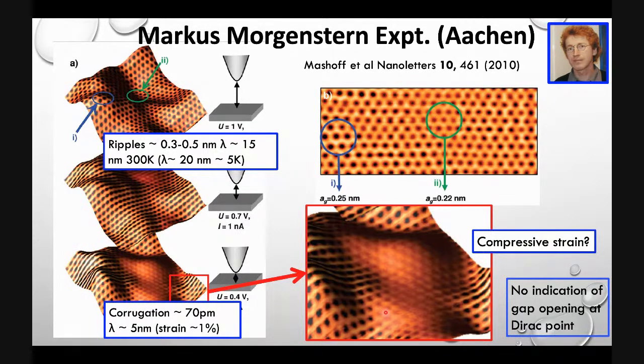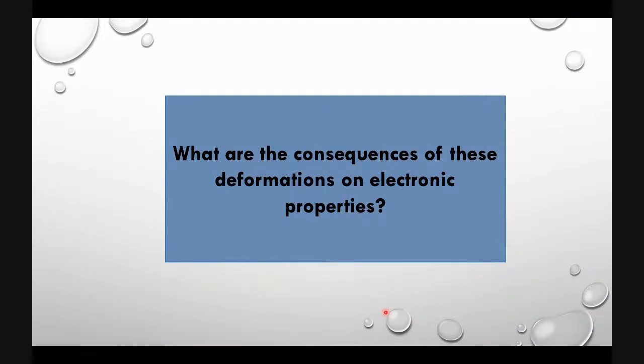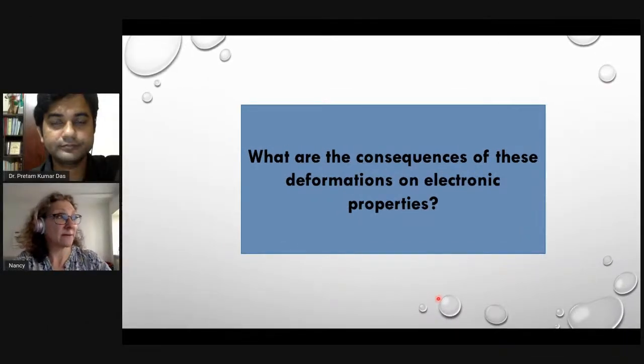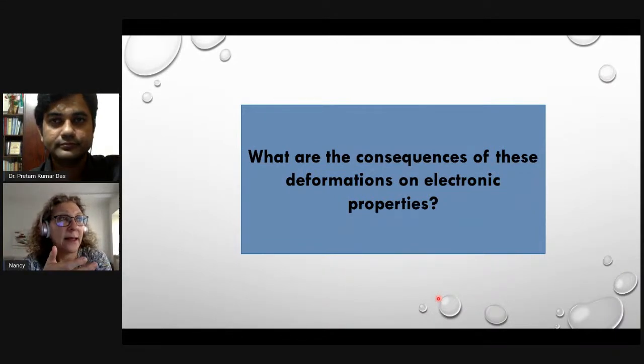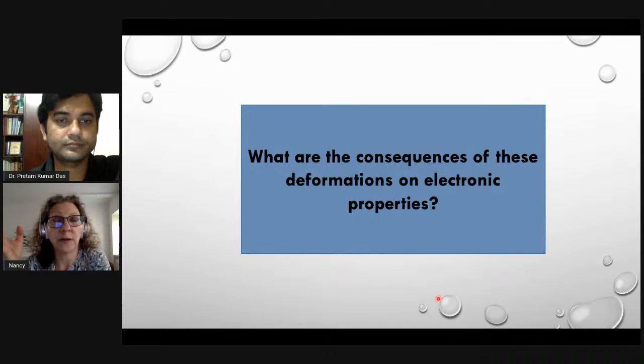And he assumed that this was because there was an underlying strain producing changes in the charge distribution that was causing these STM images. So what we set up to do in our group was to try to make a connection between the charge distribution that he was observing in these images and the strain that could occur if you deform, that is, if you separate the carbon atoms from their equilibrium positions. We wanted to see if there was a relation, and if that relation was the cause of these dramatic changes in the STM images.